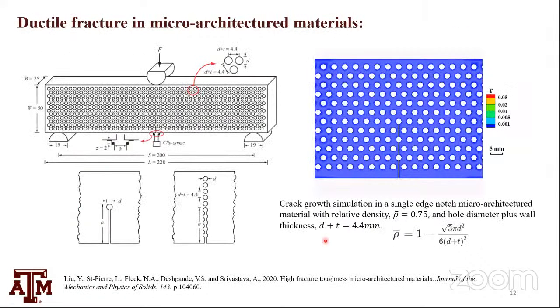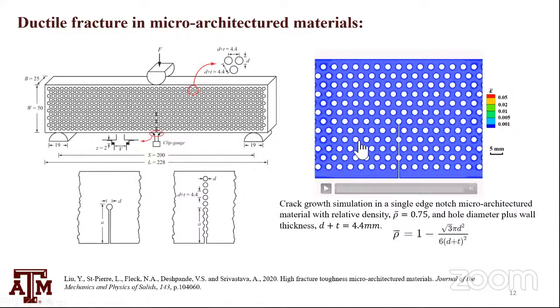Moving on, these microstructure-based models can also be used to analyze other scenarios like a microarchitectured material. This work was experimentally done by St. Pierre when he was a PhD student with Vikram Deshpande at Cambridge. He took a slab of aluminum, laser-drilled a bunch of holes, put in a notch, and did a 3-point bending fracture test. He had one hole, multiple holes, and we did finite element simulation for this problem to see whether we have a J field and can define fracture properties. So this is a simulation result.